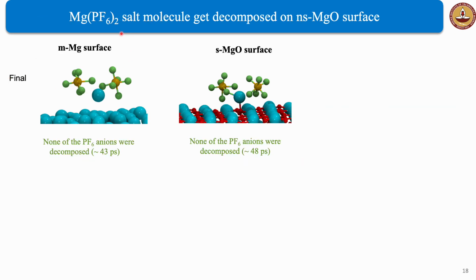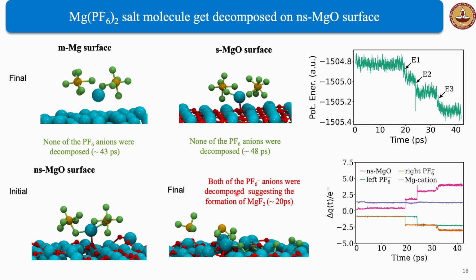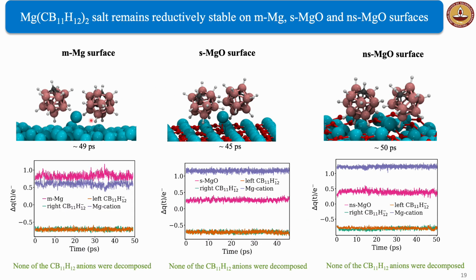Next, we check the stability of the MgPF6 salt, and similar to the MgTFSI salt, here also both the metallic Mg and s-MgO surfaces were unable to capture the interfacial reactivity of the MgPF6 salt, and both the PF6 anions remained stable. While on the ns-MgO surface, both of the PF6 anions decomposed, suggesting the formation of magnesium fluoride, in line with the experimental observations. Next, we check the stability of the carborane salt, and we found the carborane salt to remain reductively stable across all three surfaces, suggesting the high reductive stability of the carborane salt, again in line with the experimental observations.